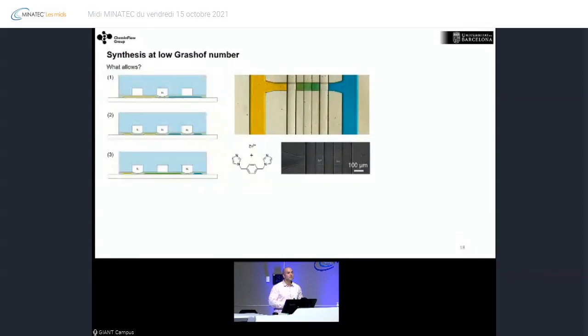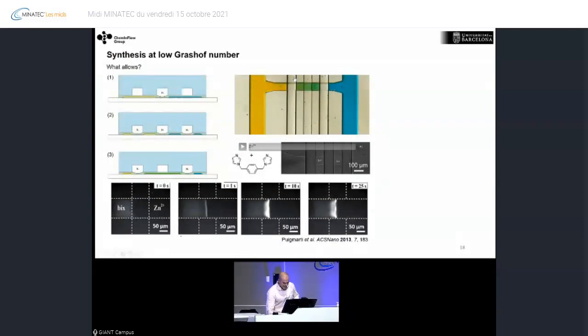So what we want to have is a free interface diffusion process. As you see there, the blue and the yellow completely diffuse, and they generate the green color in the whole area of the reaction. But we could not see what was happening really at the interface. This is why we used this imidazole derivative and reacted it with zinc, because it generates a fluorescent coordination polymer. So what you see here is this reactor. This is the valve. As soon as we open the valve, we see that we generate this fluorescent coordination polymer really at the interface of the two liquids. Because the diffusion coefficient of zinc is higher, the zinc diffuses more towards this imidazole derivative. So this clearly proves that these devices allow us to have a free interface diffusion process.